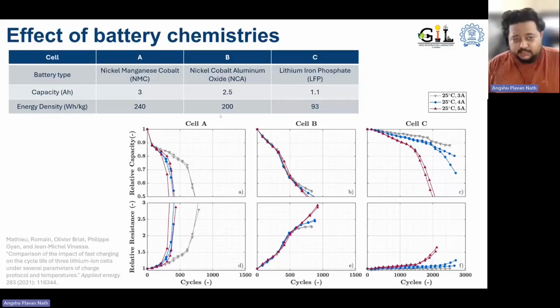So if you see here, cell A, which is a nickel manganese cobalt battery, its degradation is much faster compared to cell C. So again, it basically shows that with different chemistries we have different degradation profiles. Same with relative resistance. Resistance basically talks about power fade, so how quickly you're losing out on the power available with the battery. Cell C has a much slower, much better degradation profile. So it doesn't degrade as fast, but cell A has a much faster degradation profile.